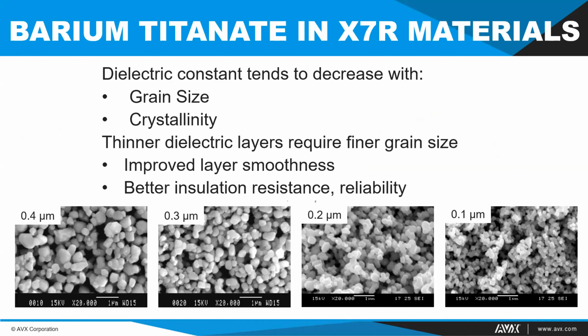This shows a little bit about the types of the changes in barium titanate that have been used over the years for X7R materials. Actually, there's a previous stage, probably maybe 30 years ago to 20 years ago, where we might have used something on the order of 1 micron down to 1/2 micron in grain size. But as layers got thinner, we found that we needed to gradually march down the grain size until you see the kinds of materials that are being used today at 0.1 micron. And the dielectric constant, unfortunately, tends to decrease over this range. But it does allow you to make thinner layers. And so you're constantly trying to modify the material to keep the highest K as possible.